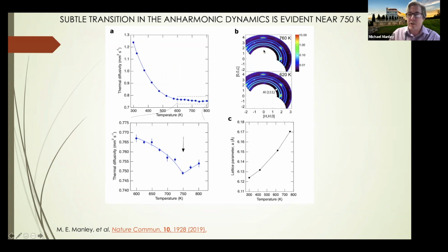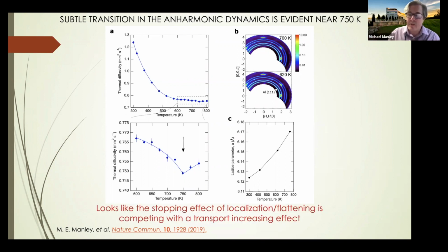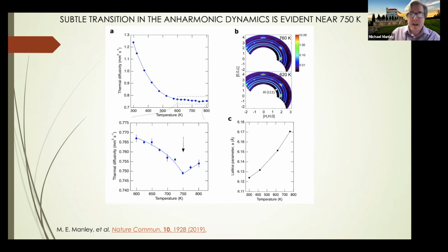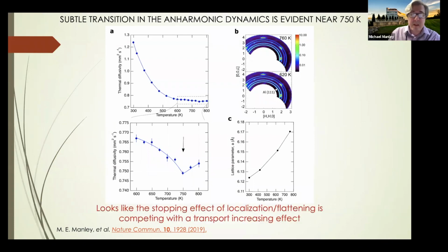Our data sets are huge. They're four-dimensional data sets. They have all the diffraction data, elastic diffuse scattering, inelastic scattering, everything. It's all contained. And this is a small section of it because this is cold neutrons. But we can measure the same phonon maybe 100 times in a single measurement, over and over again, and we measure the structure at the same time. But this is a thermal diffusivity measurement, and again we can see that at the temperature where we see this kind of jump in the lattice dynamics, we do see a kink here. It's a very subtle effect, but we see the thermal conductivity going down and then recovering back up. And remember, the LA phonon was becoming sharper. Now, I want to talk a little bit about that.